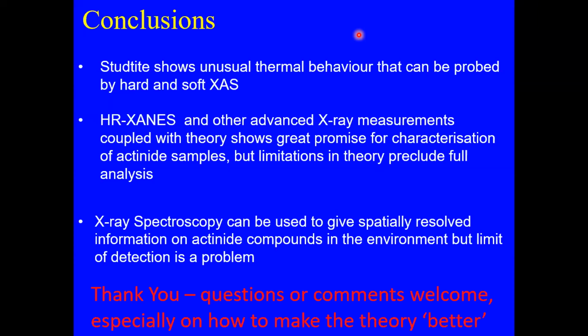And do they damage very easily in the beam? Sorry, say again. Do you observe a lot of X-ray damage? No, we didn't see very much in the way of X-ray damage, but what we were seeing was the studtite dehydrating slowly in the X-ray beam. So they weren't breaking or decomposing, but they were dehydrating, if that makes sense.